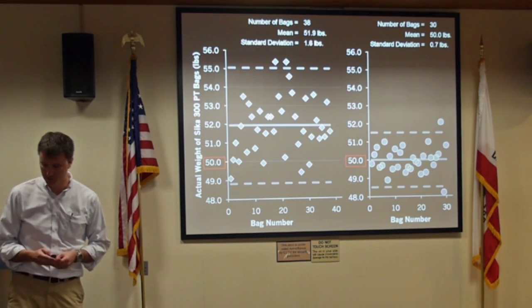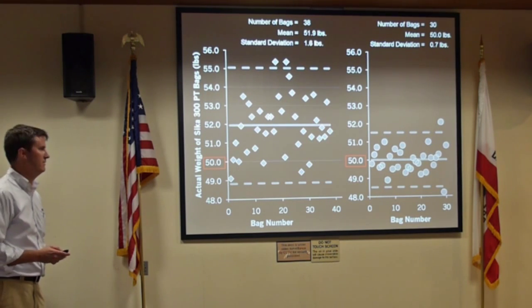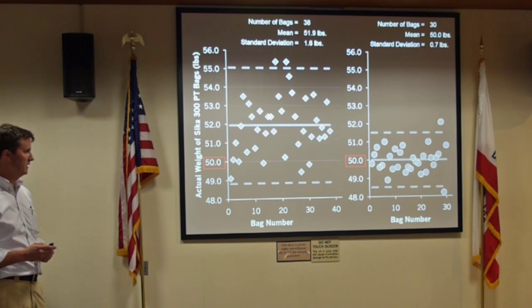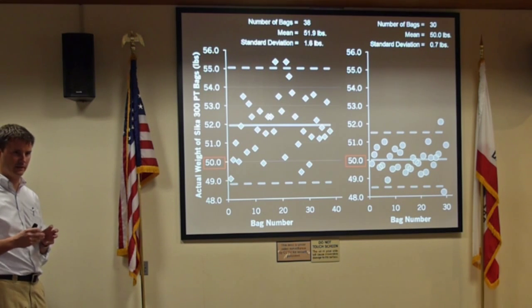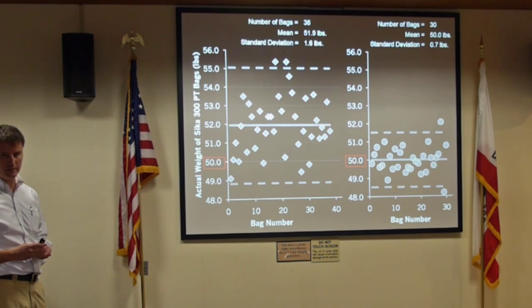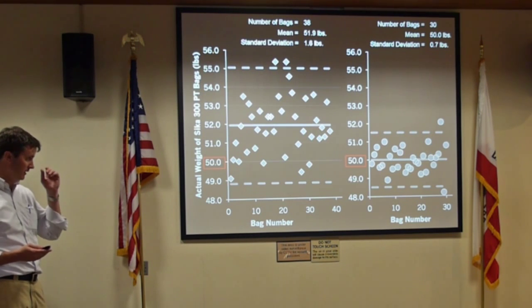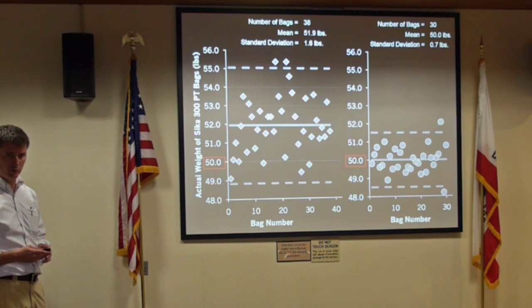And we also found that there's not a lot of quality control when you look at such things as the weight of the bags. The weight of the bags, how much water you have, goes to the water cement ratio, which has an influence on bleed. And what we found is that in one batch they had very good grouping around the nominal weight of the bag, which is 50 pounds, and then in another batch, they were all over the place in terms of how much product was actually in the bag, which will ultimately affect the performance of the material.